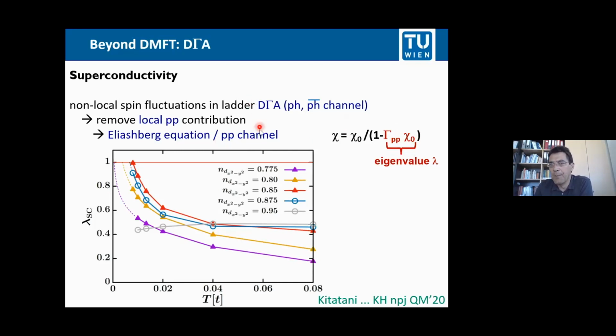So it's a poor man's version of a fully fledged Parquet D gamma A, or in a FRG way you would couple these equations. Only the first step. We don't take any feedback from the particle-particle channel to the particle-hole and particle-hole bar channels into account here. Doing that, we can calculate the superconducting susceptibility. D wave is dominant. You won't be surprised. And you see here the eigenvalue is approaching 1, which means the susceptibility is diverging in the superconducting doping regime.